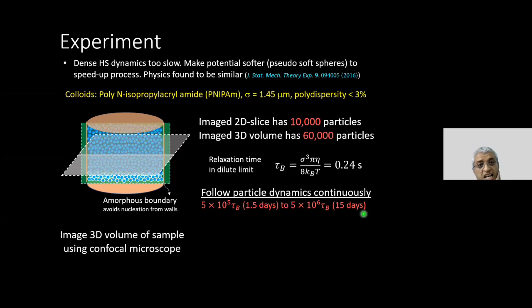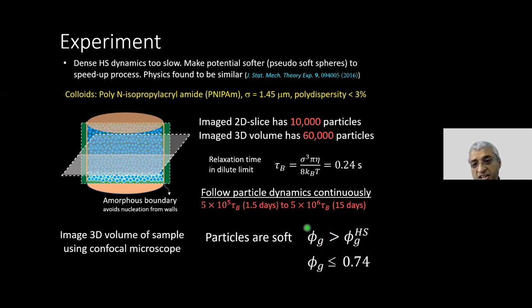Okay, so this experiment throws at us about terabytes of data, and we have to really sift through it to see what's going on. And just some detail: because my particles are soft, the volume fraction at which they become glassy is greater than the hard sphere volume fraction, and we find it to be close to 0.74.